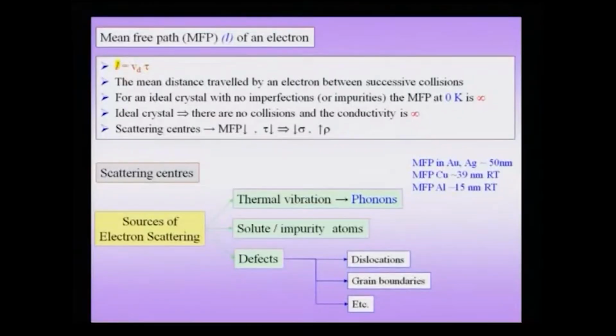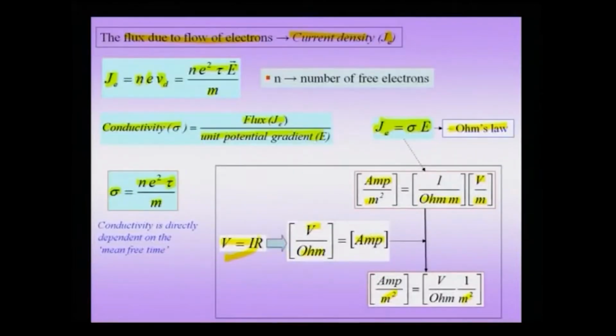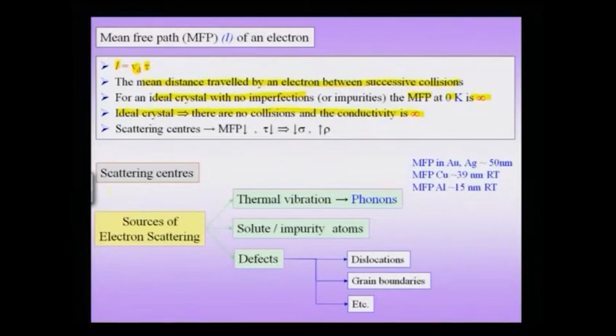Now, we have a few more things to say about the mean free path, which we had pointed out before. The mean free path can be written down as the drift velocity times the average collision time. This is the mean distance travelled by the electron between successive collisions. For an ideal crystal with no imperfections, we expect the mean free path at 0 Kelvin to be about infinity. That means in an ideal crystal there are no collisions and the conductivity is infinite, because the average collision time is directly proportional to the conductivity, and if it goes to infinity, the conductivity goes to infinity. But as I pointed out, there are scattering centers in the material which reduce my mean free path and therefore increase the resistivity of the material.